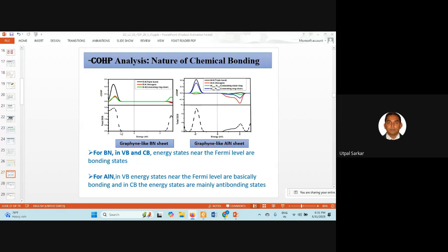It is in the valence band. BN at the hexagon and BN concentrating at the ring, these three we have considered, and all are basically in the valence band, all are contributing. So BN in the VB and CB energy states near the Fermi level are bonding states. You see here, they all are positive. But for aluminum nitride, in the valence band it is basically positive, but here you see, in the conduction band these are basically antibonding states. So bonding and antibonding character for this chemical system, or any periodic chemical systems, you can also analyze through quantum mechanical calculations.